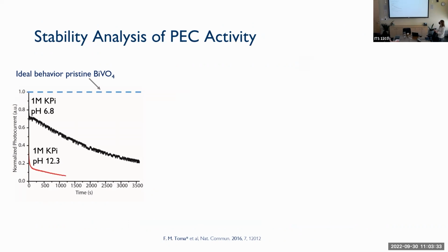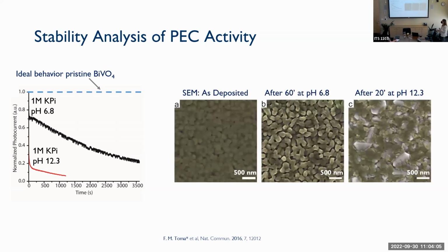Because ideally, and this is normalized photocurrent, just for simplicity, ideally what we would like to have is that your material is just really stable and stays at 1. But this is a near neutral pH, so very gentle conditions if you want. But already after 1 hour, the photocurrent is almost done. At pH 12.3, which is usually a good pH to perform water oxidation, the situation is even worse. After 10-20 minutes, the material is completely done.